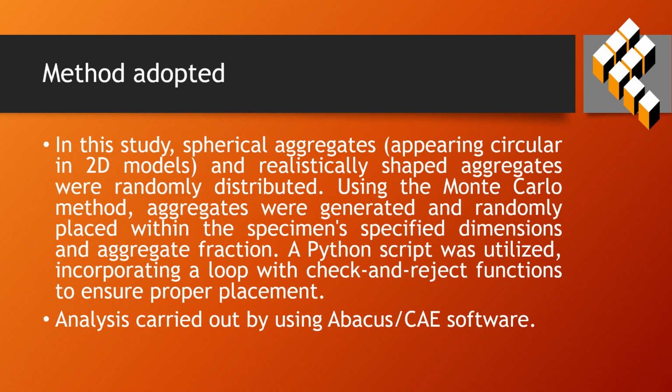In this paper, the method adopted uses two types of aggregates randomly distributed, that is spherical aggregates as well as realistically shaped aggregates. These two aggregates are distributed in the concrete by using a Python script, and then the entire model is simulated using the Abaqus CAE software.